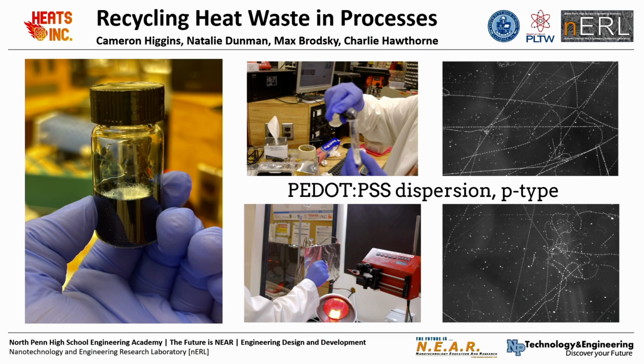Building on our research with prefabricated commercialized thermoelectric generators, we set out to make our own. To do this, we used a PEDOT:PSS aqueous dispersion, which is essentially a solution that contains PEDOT, which is currently the most thermoelectrically efficient known organic compound, and PSS, which is an additive that increases its solubility and also acts as a counter-ion during thermoelectric conversion.